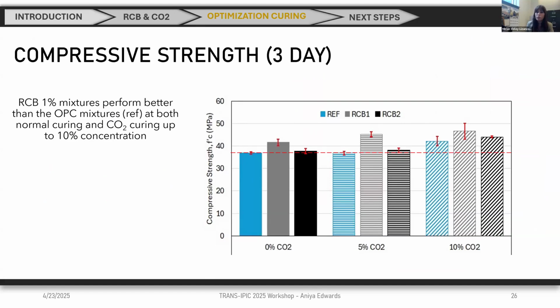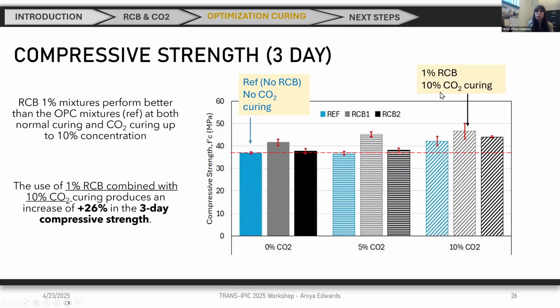So here you can see the compressive strength. I am showing just 0, 5%, and 10% CO2 concentration. And one thing that you can see is that with 1% recovered carbon black, in all cases, we have a higher strength than with no carbon black. So 1% carbon black increases the early strength. But not only that, if we focus on no CO2 curing, no carbon black versus 1% recovered carbon black and 10% CO2 curing, you will see that we are having an increase in the compressive strength of 26%.